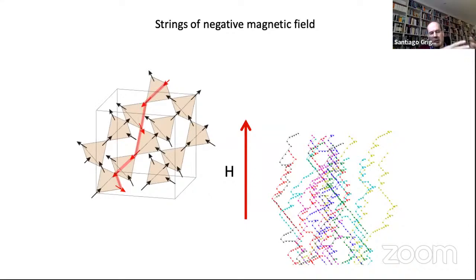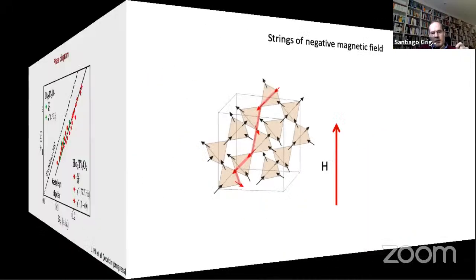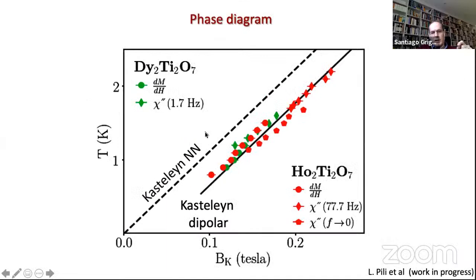One thing I wanted to say before was that the main difference between these two lines is that here in the nearest neighbor approximation, essentially there's absolutely no interaction between these lines you've created, while this is not necessarily true, and that's the difference. That's why this line shifts when you have dipolar interactions. So once you add the dipolar interactions, you see that these lines interact with each other. They don't particularly like being next to each other, right?